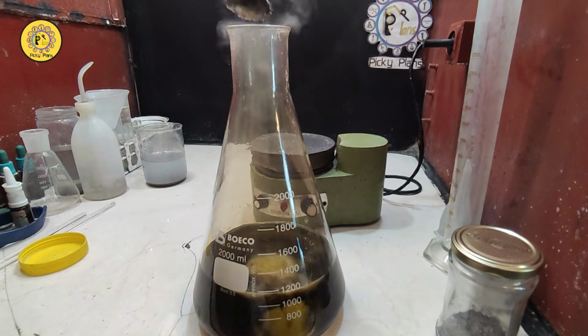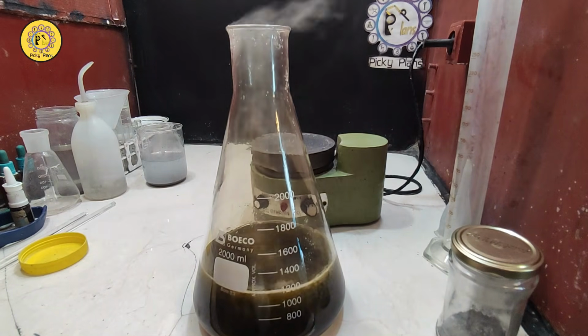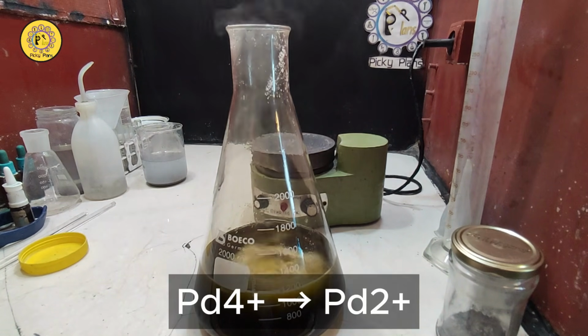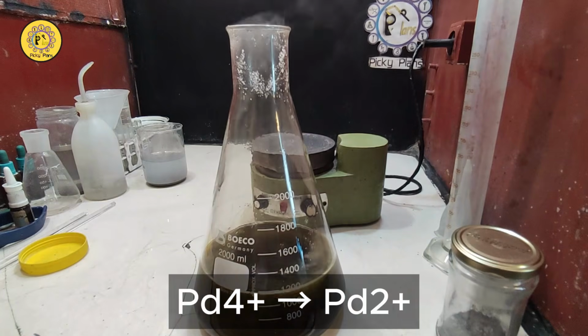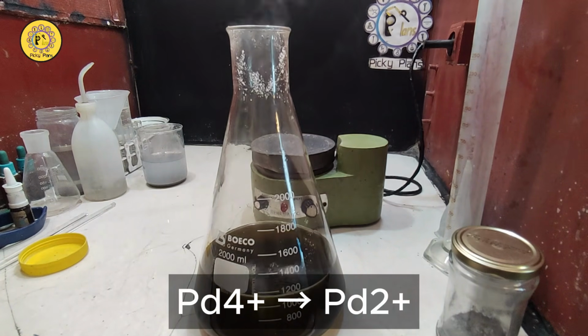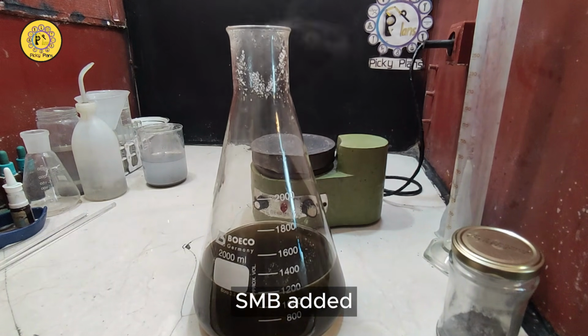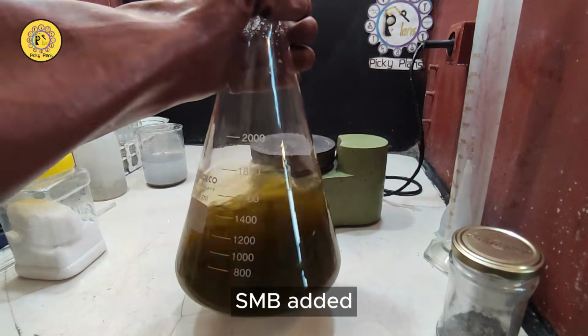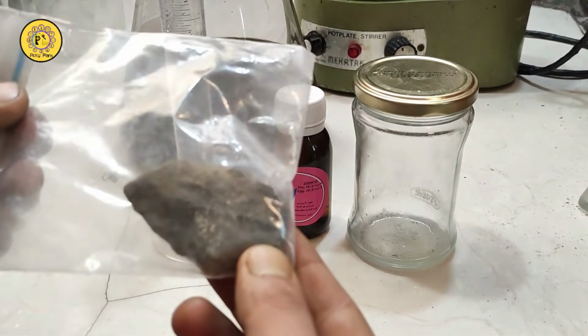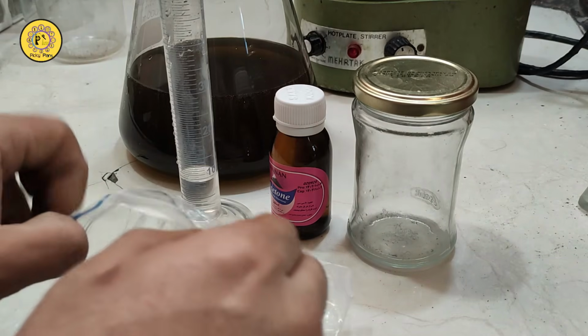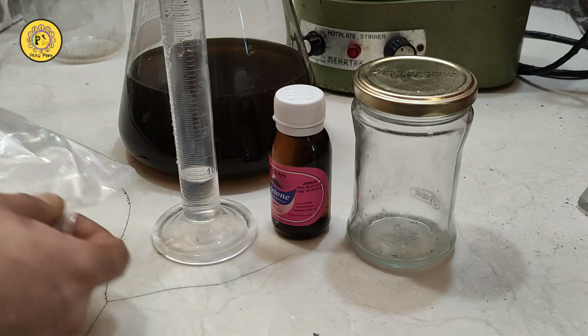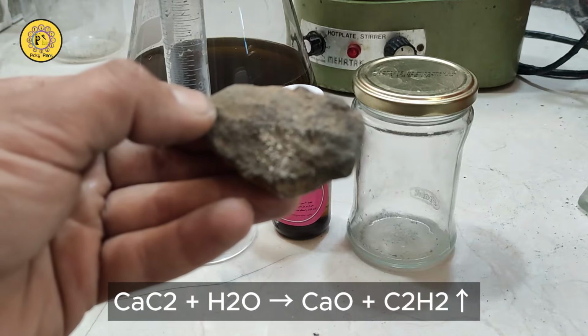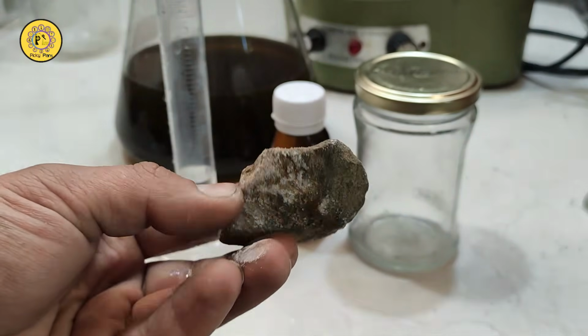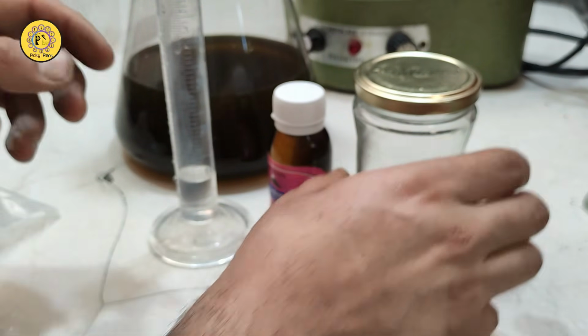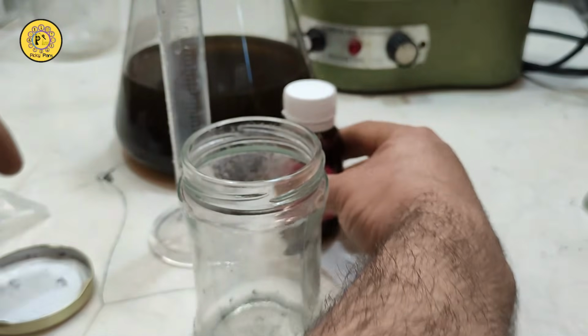To precipitate palladium carbide, you need to reduce the 4 plus charge palladium ion in the solution to the 2 plus charge. To do so, I added some sodium metabisulfite. The solution is ready to precipitate palladium. I use calcium carbide to generate acetylene gas, which reacts with palladium to form palladium carbide. Calcium carbide is easily accessible.